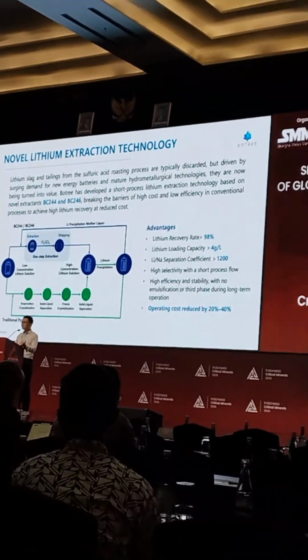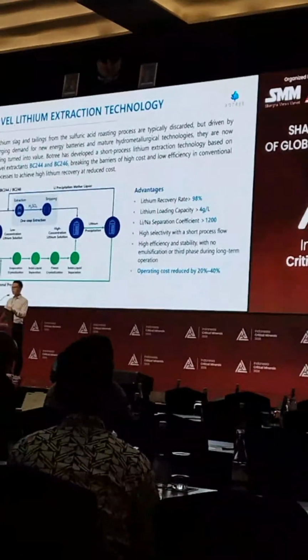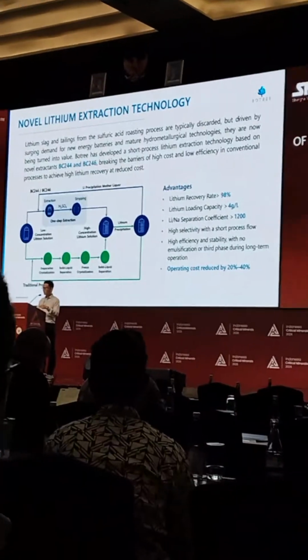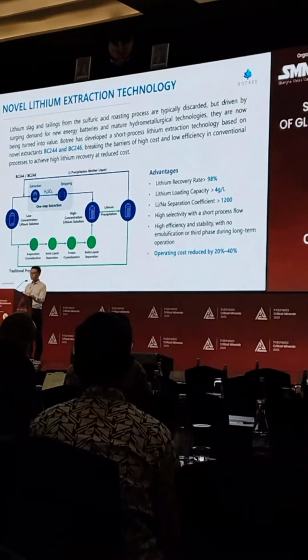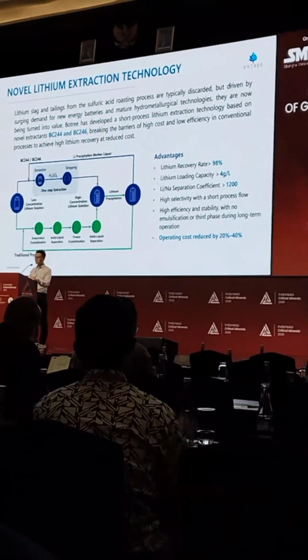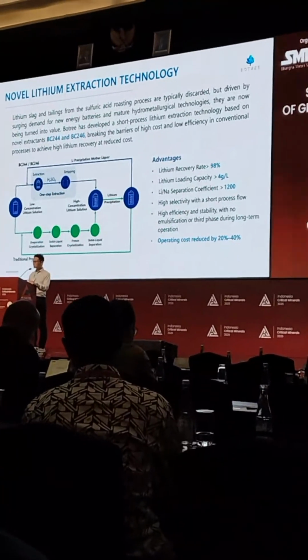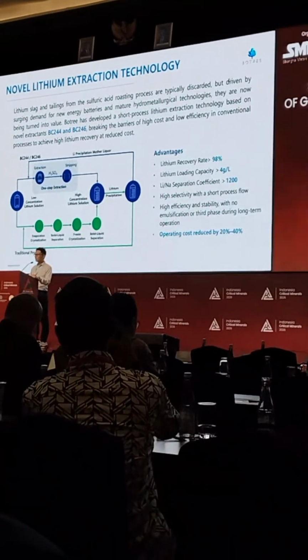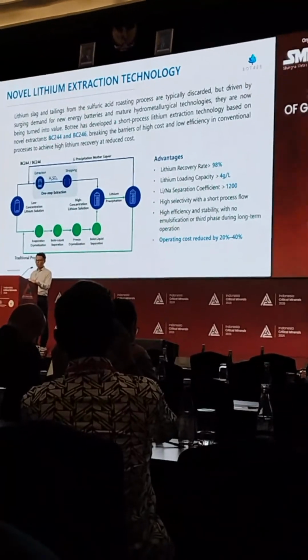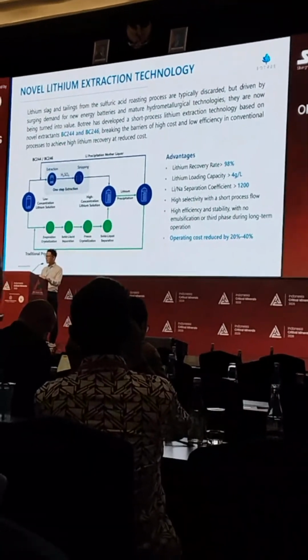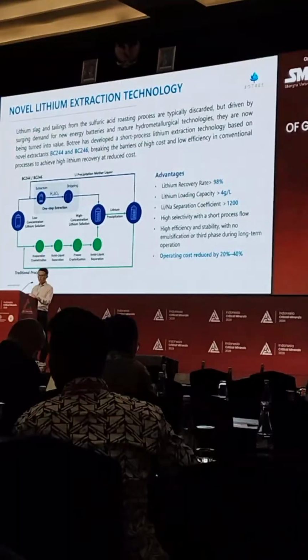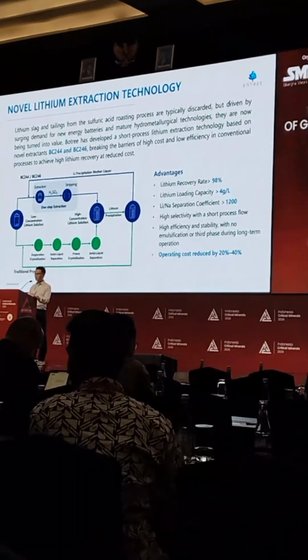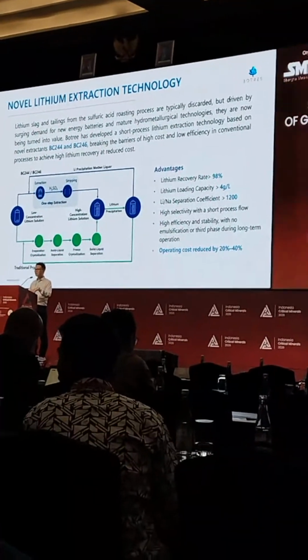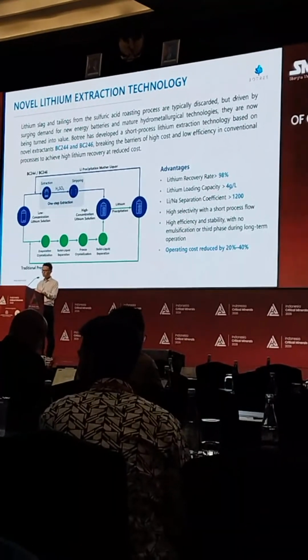In addition to the nickel and cobalt, what we are doing now is also lithium extraction. It means that we can do the extraction of the lithium instead of the MVR concentration. We can decrease the capex and also the opex. The lithium recovery efficiency can even be increased using this technology.